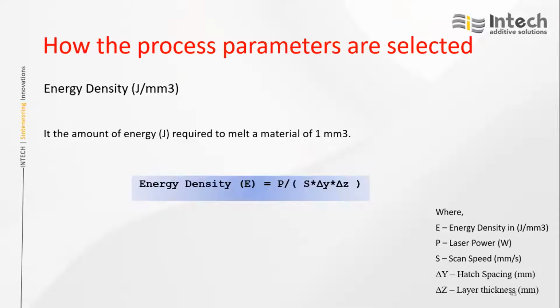Once we arrive at the energy density, we have to split that energy density into process parameters: laser power, scan speed, hatch spacing, and layer thickness. Energy density is nothing but laser power divided by scan speed into hatch spacing into layer thickness.